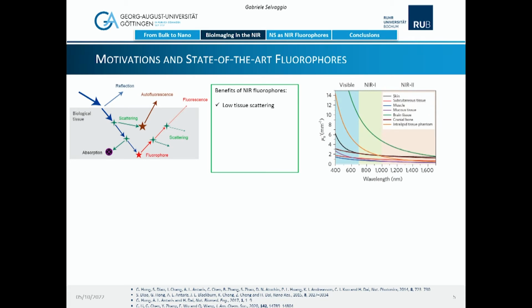If you notice here, we have wavelengths in the x-axis. This is a typical visible region till 700 nanometers. And from 700 nanometers onwards, you have the near infrared 1 and near infrared 2 regions. And you see the tissue scattering is decreasing with increasing wavelengths.